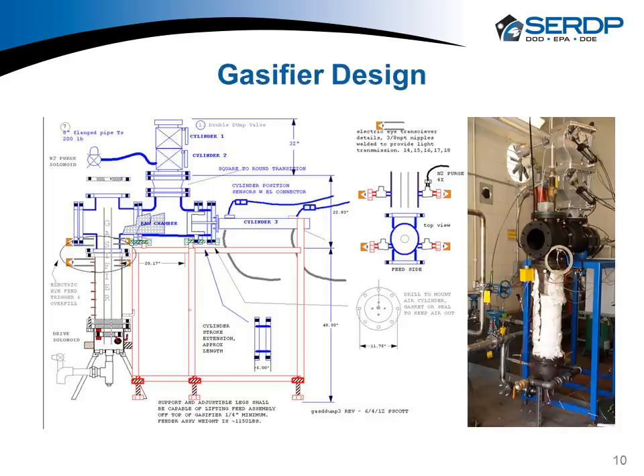So here's the gasifier in cross-section. I apologize for the busy charts. I'm kind of famous for them. But basically, we have a double dump valve that drops the waste product, or the feed, in front of a hydraulic or pneumatic ram that's going to push the material to the mouth of the gasifier where it drops in. We wanted to leave a plug of material here to act as a tar shield to keep tar from going back and coating all the work. So we only push about halfway, and then we get this plug of material going through. It's not an airtight plug by any means, but it did, in fact, condense the tar.